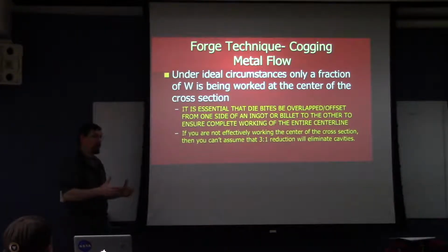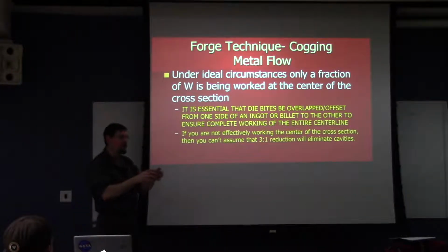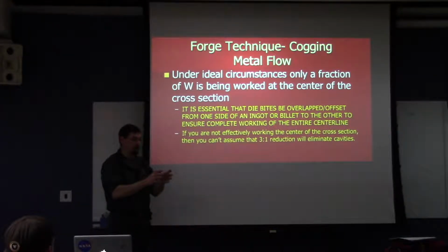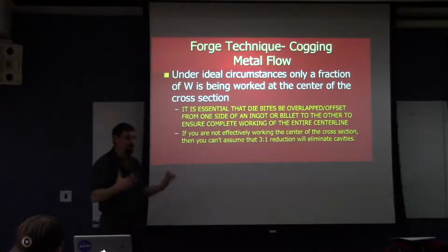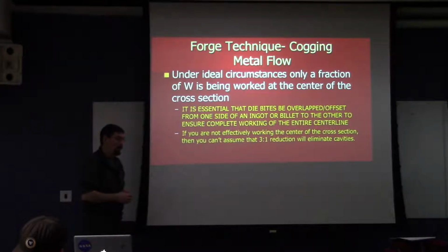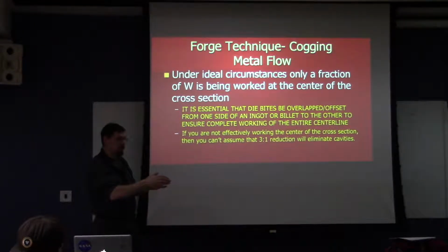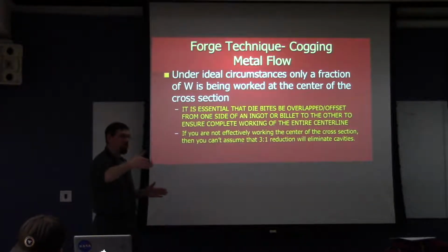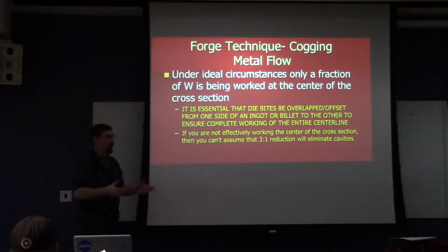If we don't do that, we'll end up with areas that are left with these shrinkage cavities along the center line. I've seen results from our non-destructive evaluations where they do an ultrasonic test and you've got a section that's nice and good, there's no indications, and then a section with indications, and they're very evenly spaced down the length of a bar. And right away I know that there was an issue with the overlapping on that bar, and that's why those holes exist there.